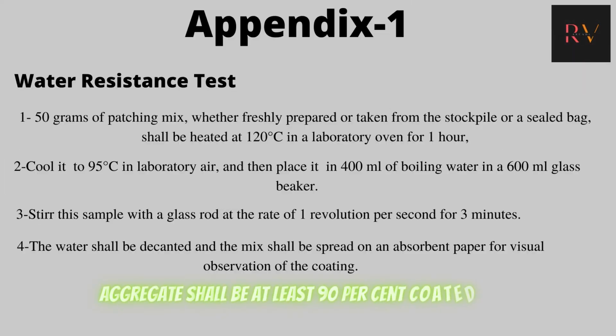Now coming to water resistant test. 50 gram of patching mix, whether freshly prepared or taken from the stockpile or a sealed bag, shall be heated at 120 degrees Celsius in a laboratory oven for 1 hour. Cool it to 95 degrees Celsius in laboratory air and then place it in 400 ml of boiling water in a 600 ml glass beaker. Now stir this sample with a glass rod at the rate of 1 revolution per second for 3 minutes. The water shall be decanted and the mix shall be spread on an absorbent paper for visual observation of the coating. Now in this, aggregate shall be at least 90% coated with the bituminous film.